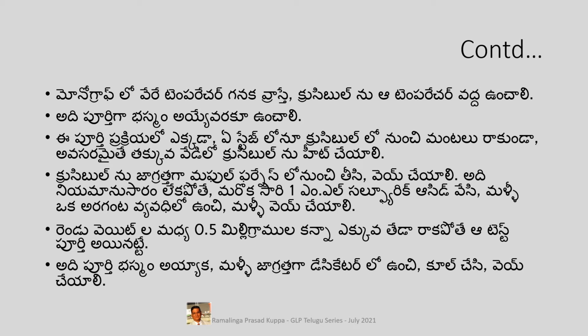Once the complete ashing is done, take out the crucible from the muffle furnace carefully, cool it in the desiccator, and weigh it, and calculate the sulfated ash. If the ash content is not within the specifications, again add 1 ml of sulfuric acid to it and heat for another half an hour. And cool it again and calculate the sulfated ash again. If the difference between two weights is less than 0.5 milligrams, then that is considered as constant weight, and we assume that the test is complete. Once the total ash is done, you have to carefully put it in the desiccator, cool, and weigh that.